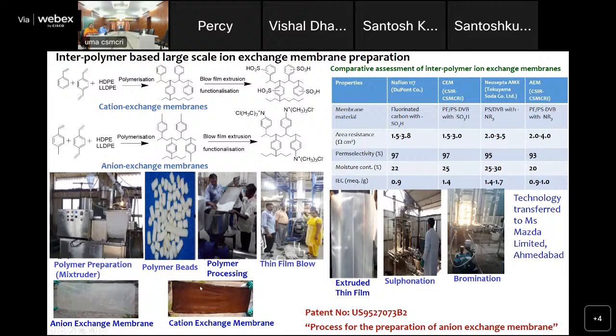This is the digital image of the cation exchange membrane. The anion exchange membrane is prepared from the interpolymer of polyethylene and vinylbenzyl styrene divinylbenzene. Once the polymer is prepared, it is also converted to a thin film of thickness 150 to 160 micron, and then benzylic bromination of this interpolymer film is carried out. The positive charge is then introduced by dipping that brominated film into a trimethylamine mixture, and this is the digital image of the anion exchange membrane.